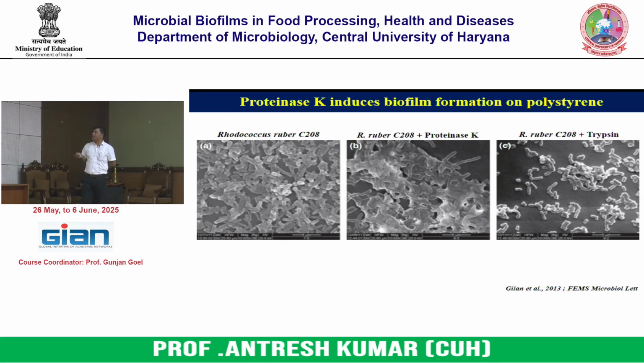stable, multi-layered. This is because proteinase K degrades the detachment signaling, leading to the formation of a multi-layered, non-dispersed biofilm as compared to this. And ultimately, they have also concluded there are certain kinds of enzymes that can be inhibited by trypsin. As a result, the detachment occurs. And in this case, it induces some kind of signals that can induce quorum sensing. As a result, there is more biofilm, but the nature of the biofilm gets changed. In this case, a multi-layer biofilm is formed by the proteinase treatment of Rhodococcus ruber.